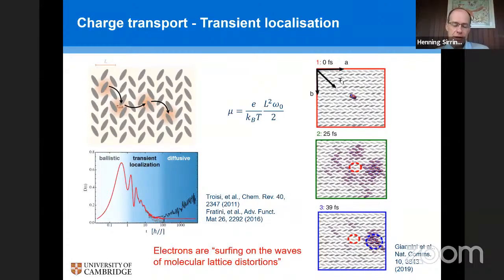It was developed by two theoretical groups, Alessandro Troisi, who is now in Liverpool, and Simone Fratini at Grenoble in France. And the picture is essentially that if you induce a charge into a molecular lattice, this charge sees a dynamically fluctuating environment of transfer integrals. The Hamiltonian has not static transfer integrals, as you might assume in a more covalently bonded system, but has all these temporally fluctuating transfer integrals. And that leads to a localization of the charge carrier.